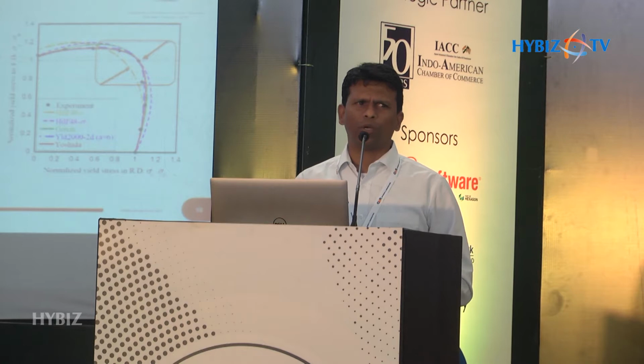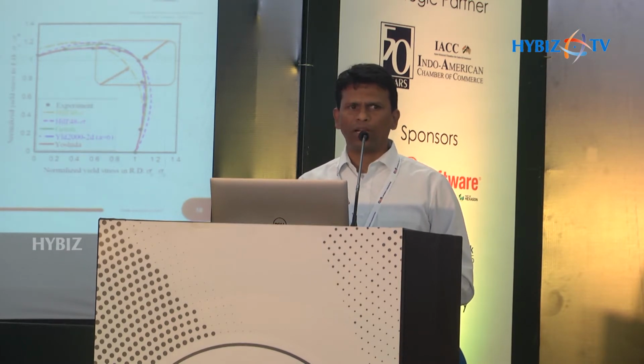And normally if you don't capture the exact material behavior, the standard thing that everyone tries to do is a tensile test of the specimen, and then take the information coming from the tensile test specimen, like YS, UTS, percentage elongation, anisotropic value. But this is not sufficient if you are working with a high tensile, a special material or advanced materials. So you end up with a wrong prediction of your failure itself. If you could see here, the failure is at 0 degrees, and the simulation, taking into account the realistic behavior into the simulated value, is giving you a failure at 45 degrees. So the basic test itself is failing, which means if you go forward, you will not be able to correlate your results with the actuals. So the main reason for us to understand the yield locus, the yield behavior of your material, is that if you don't understand it well, you are not doing it right.